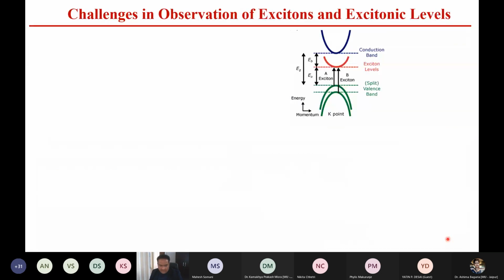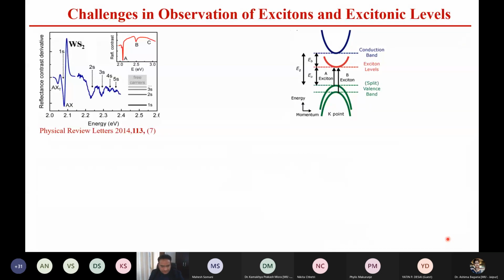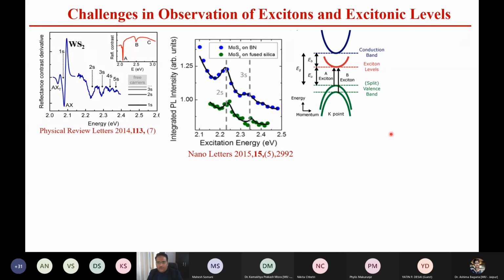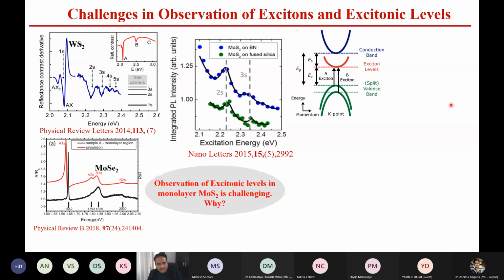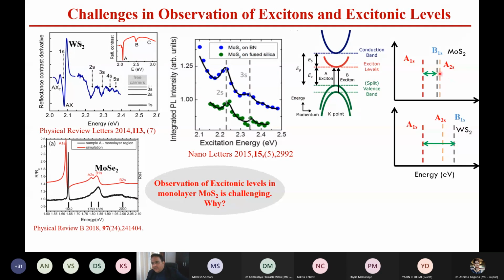Now coming back to MoS2, people have tried to understand whether you are able to see those excited states. For example, in WS2, people are able to observe the 1s excited state, 2s excited state, 3s excited states of the excitons, the A, B, C excitons, but in MoS2, it's very difficult. The reason being, in the case of MoS2, the spin orbit coupling because of the molybdenum, okay, is very small.